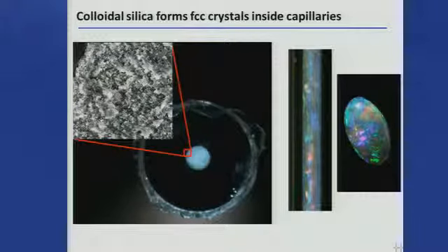And so my students are making these in all sorts of media, and we've done a lot of work with packing capillaries with these. My student Bing-Chuan Wei packed this 75 micron ID capillary, so this is the plastic cladding around the capillary. And we took a color photo of it in a zoom microscope, really tiny domains, and then we have a scanning electron microscope right next to the optical microscope, and so we moved it over without changing the orientation and took an SEM of this little region here, so that use a small enough region so that you can still see the curvature a little bit, but you can make out the silica particles, and so you can see these little tiny domains, and so that's what we use in chromatography. So we don't need to have enormously large domains.